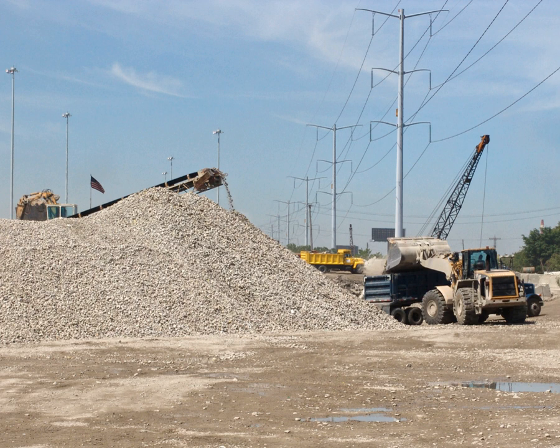This is primarily the result of the fact that the materials used in concrete construction, such as aggregates, pozzolans, and water, are relatively plentiful and can often be drawn from local sources. This means that transportation only accounts for 7% of the embodied energy of concrete, while the cement production accounts for 70%. With a total embodied energy of 1.69 gigajoules per ton, concrete is lower than any other building material besides wood.